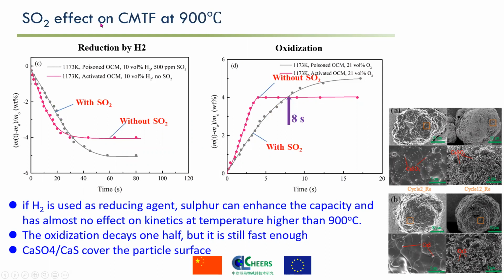Then we studied the sulfur effects on the CMTF kinetics at 900 degrees. Sulfur almost has no influence on the reduction rate. There is a benefit: sulfur can increase the oxygen transfer capacity. Also, because of sulfur, the oxidation kinetics decay by half, but the reaction rate is still fast enough. It just takes 8 seconds to regenerate 4% oxygen. From the SEM images, sulfur can react with CMTF to form sulfate, cover the particle surface, and further affect its reactivity.